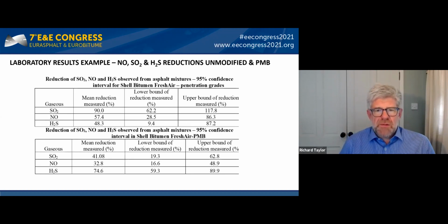Well, if I look at a sort of subset here from the thousands of tests that we had, this is the 20 penetration grade bitumens across the range of temperatures, and the same with the PMBs. We found pretty large reductions actually in the gaseous species. And so if we look at the penetration grade reductions for SO2 and NO, we're seeing certainly more than 50% for the SO2 at 90, and then in the PMBs we're seeing similar kind of reductions here in terms of the mean reduction of 40% SO2.